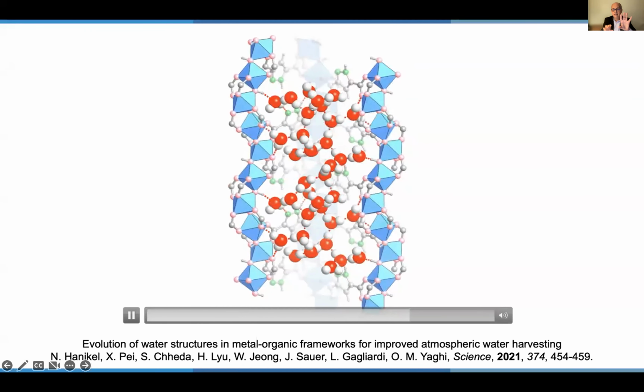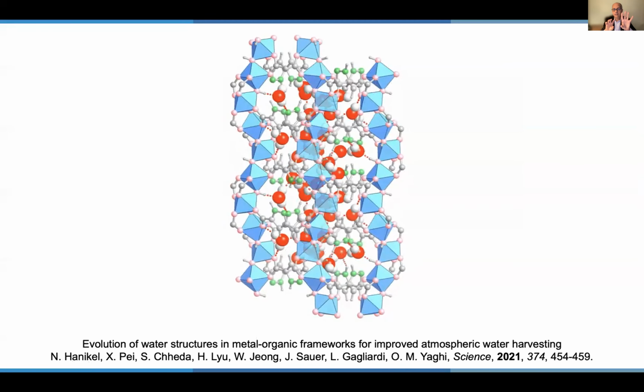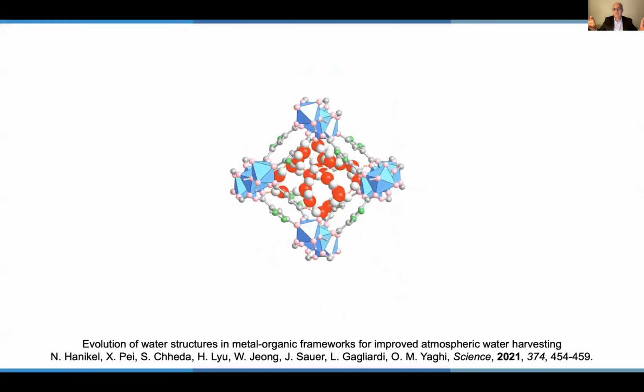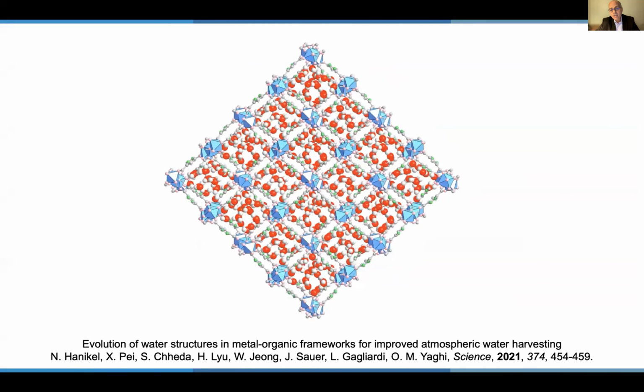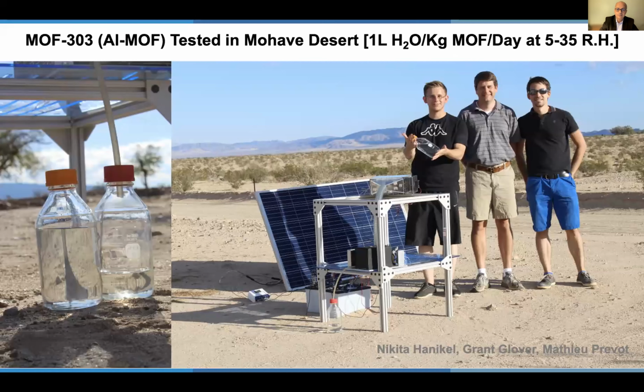So the interior of the pores is decorated by hydrophilic and hydrophobic pockets that repeat throughout the crystal. And this hydrophilic push-pull interaction with water allows you to also modulate the temperature at which water can be released. So based on that MOF, we call it MOF 303, and it's an aluminum MOF, the students can harvest 1 liter of water per kilogram of MOF per day. And you'll see from David that we have done much better now as we are teaming up with GE.